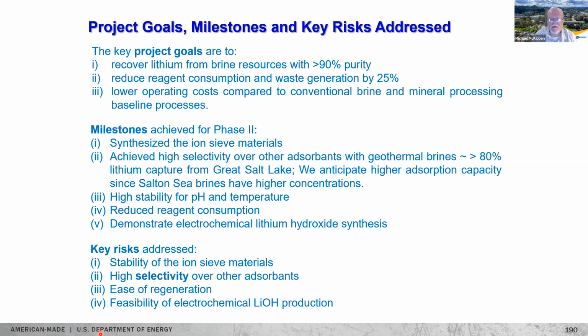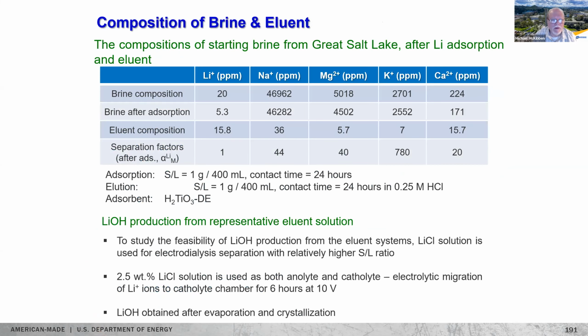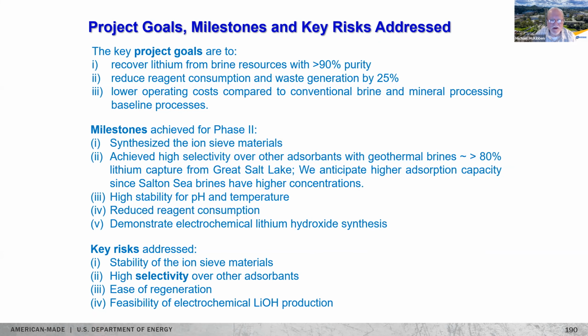Milestones achieved from this phase include synthesizing the titanium ion sieve materials, achieving higher selectivity for lithium and nearly 80% lithium capture from Great Salt Lake brines, demonstrating higher pH and thermal stability, reducing reagent consumption, and demonstrating lithium hydroxide conversion using electrodialysis. Key risks that we addressed include the stability of the ion sieve materials, the high selectivity over other adsorbents, the ease of regeneration, and the feasibility of electrochemical lithium hydroxide production. Next slide, please.